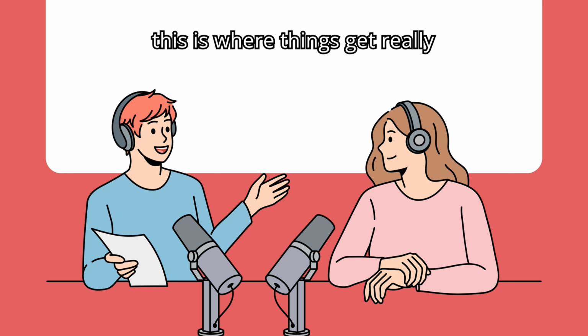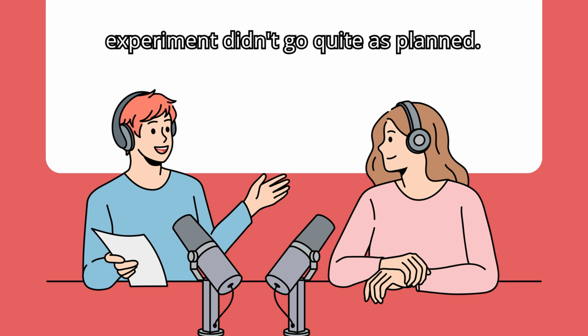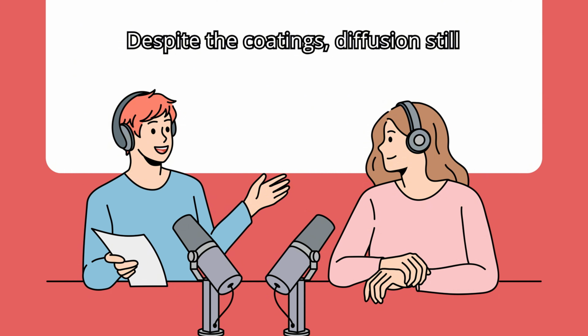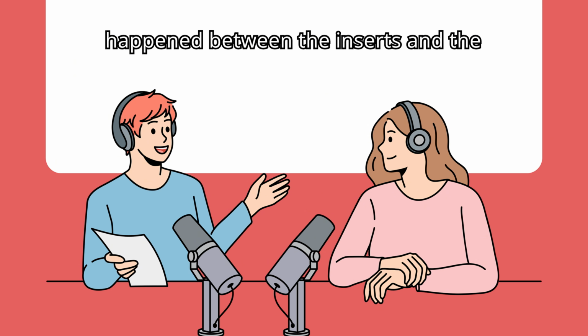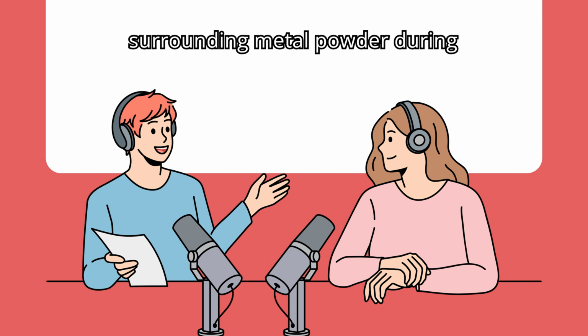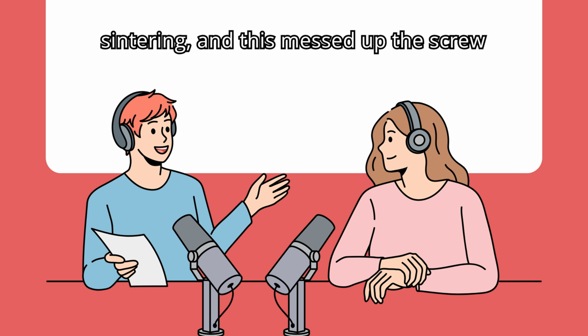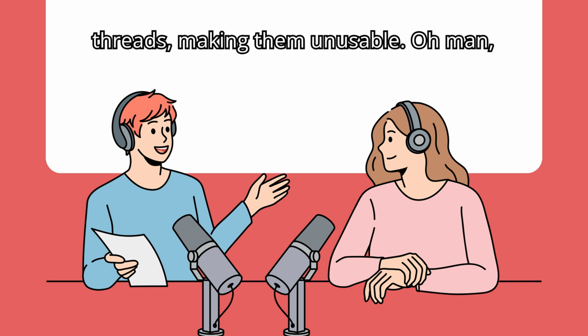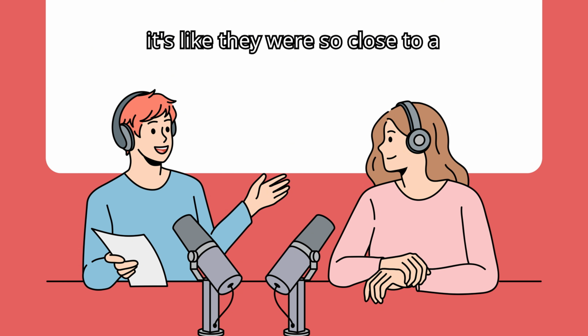Well, this is where things get really interesting and a bit disappointing. The experiment didn't go quite as planned. Despite the coatings, diffusion still happened between the inserts and the surrounding metal powder during sintering. And this messed up the screw threads, making them unusable. Oh man, it's like they were so close to a breakthrough.